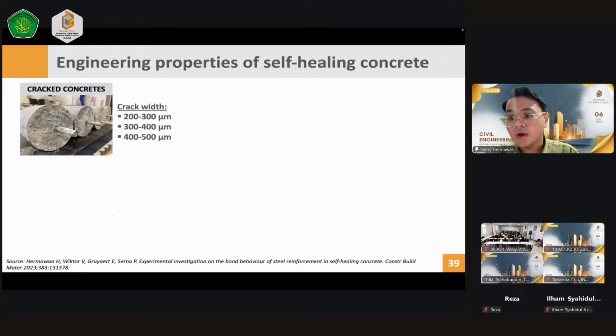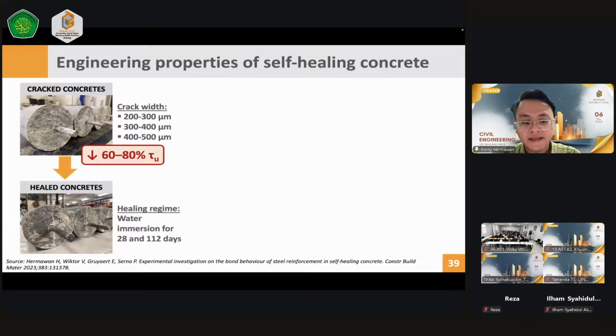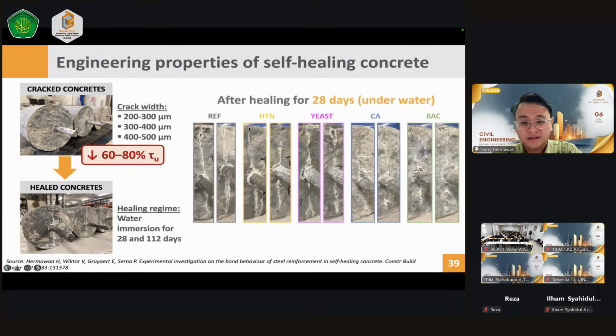So next, with the pull-out specimen, we can try to crack the specimen with a certain crack width, and with the cracking, typically we will see a reduction of the ultimate bond strength by a maximum of 80%. And then we can also submerge this specimen underwater in order to promote healing. Now I will show you a very interesting figure. After 28 days of healing underwater, you see on the crack line or on the crack mouth there was a formation of white particles. These white particles are the minerals, or calcium carbonate, forming at the crack location.